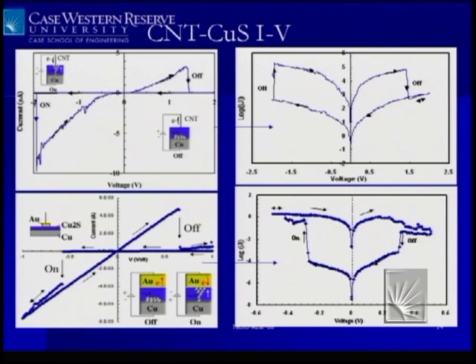These are some of the IV characteristics. I really don't want to bore you guys with lots of these details, but the important thing is that you see this on and off behavior. And these are the world's smallest area devices that are not done using electron beam lithography or X-ray lithography or some fancy technique. You grow carbon nanotube onto a functional layer, and you get 3 nanometer squared area.